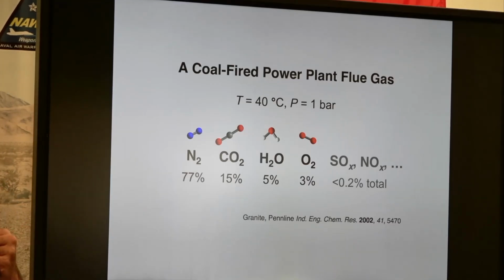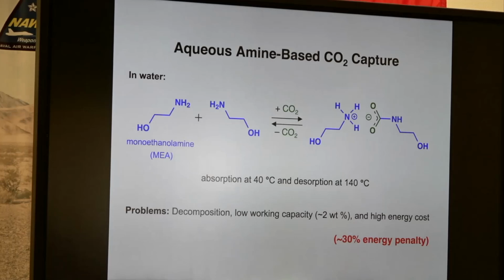And the way to do it is take advantage of the fact that CO2 is acidic, whereas the other molecules are not. And so this is what's going on in that giant tower in the Petra Nova power plant capture unit. You're taking an aqueous solution of some organic amine, a molecule like monoethanolamine, and two of these organic amine groups will capture one CO2 molecule by becoming an ammonium carbamate. And this works very well. But this is not cooperative. And so the response of these solutions is a Langmuir type of adsorption behavior. It means that once you saturate that solution and want to desorb CO2 and use it again, you have to drive to extremely high temperatures, and there's a huge energy penalty for doing that.